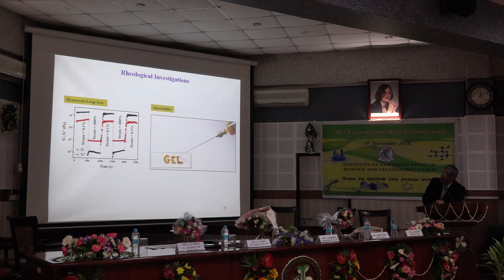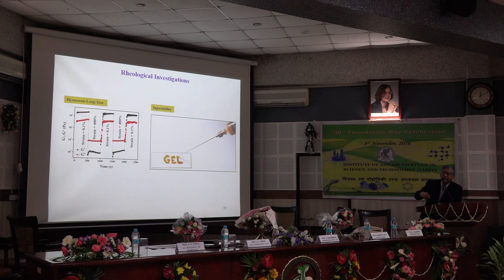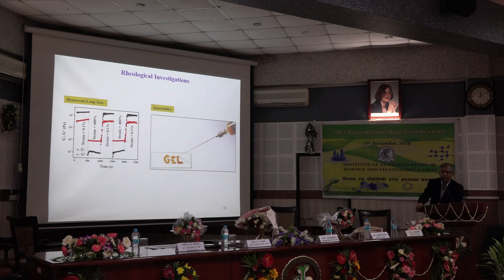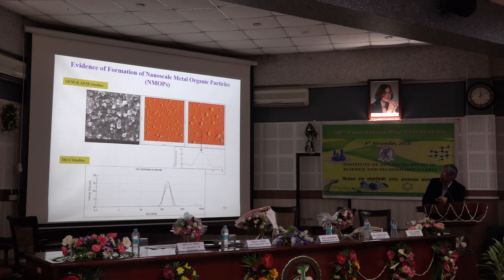We can make injectable materials. This is a hysteresis loop test. The simple physics: you boil rice and you produce a white material. It forms a gel if you pull it; if you shake it, it becomes a liquid, but if you put it to rest, it becomes solid again — these are called thixotropic materials. So this is also a thixotropic material. They also form nanoscale metal-organic particles, and you can follow them by dynamic light scattering, scanning electron microscopy, atomic force microscopy, and of course X-ray crystallography.